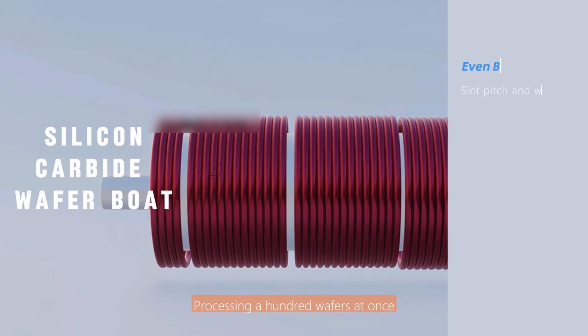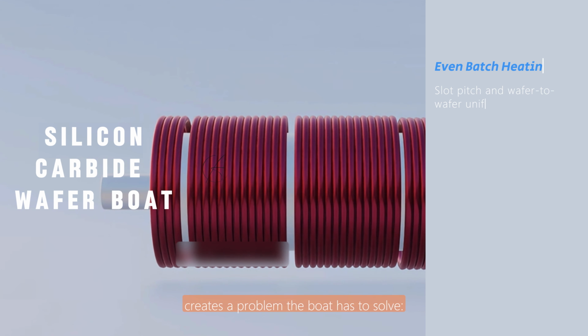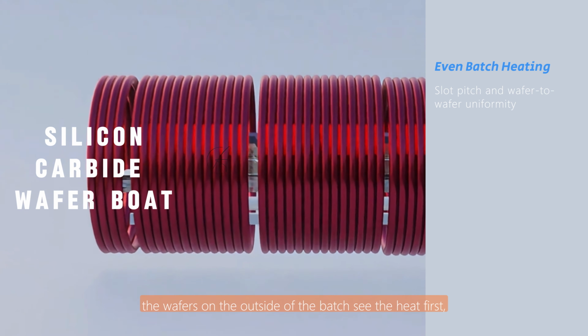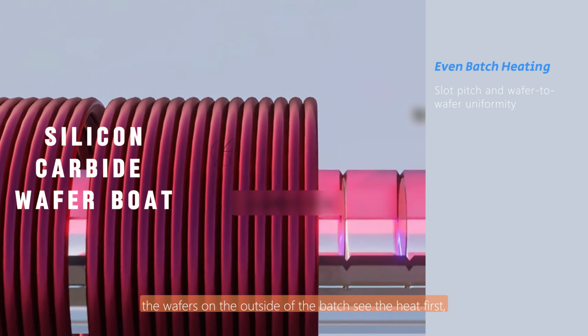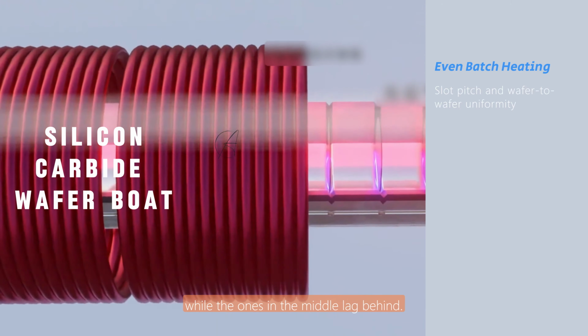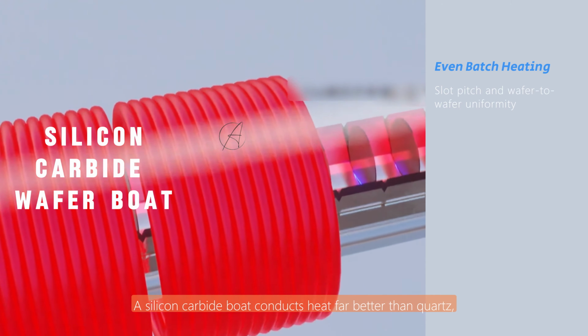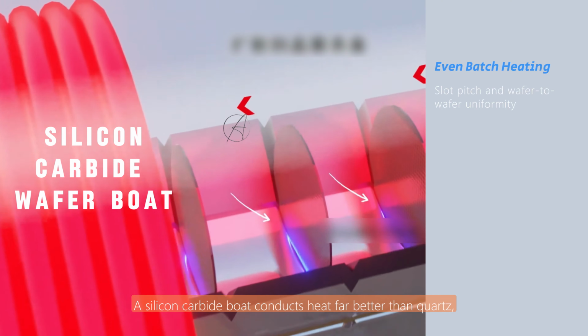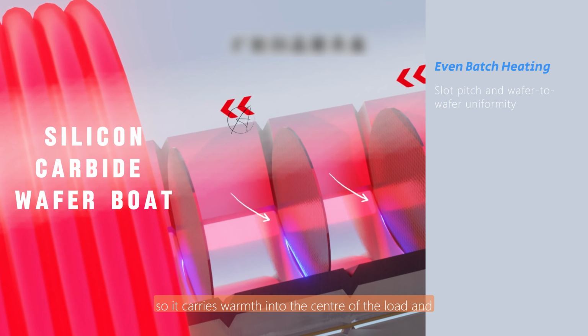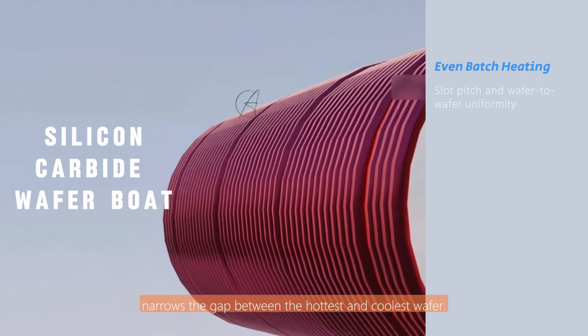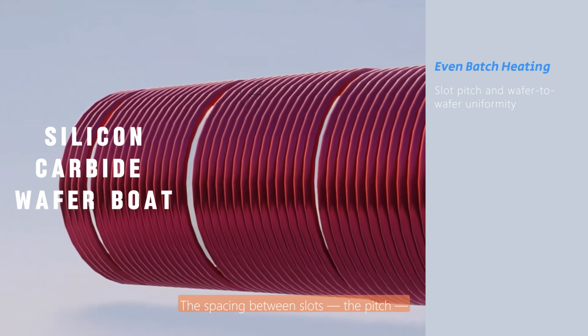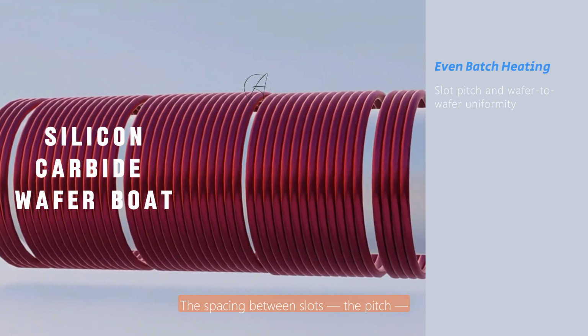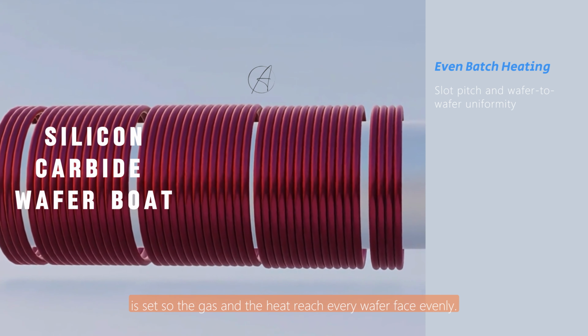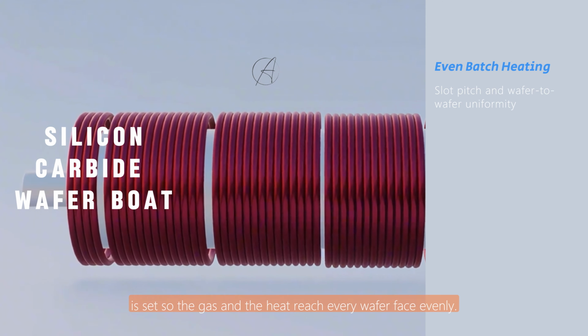Processing 100 wafers at once creates a problem the boat has to solve. The wafers on the outside of the batch see the heat first, while the ones in the middle lag behind. A silicon carbide boat conducts heat far better than quartz, so it carries warmth into the center of the load and narrows the gap between the hottest and coolest wafer. The spacing between slots, the pitch, is set so the gas and the heat reach every wafer face evenly.